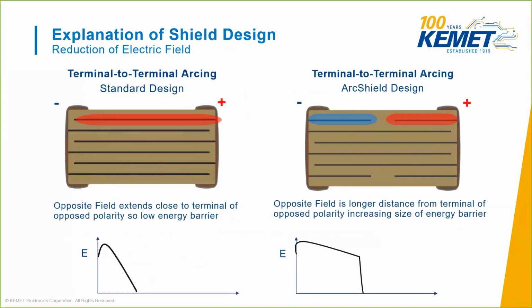Now, to go into a little bit of further explanation, you can see here a standard design on the left, and this really has an opposite field that extends close to the termination of the opposed polarity. So there's a low energy barrier in this region right here, so you get a high field concentration between the termination and the first opposing electrode.